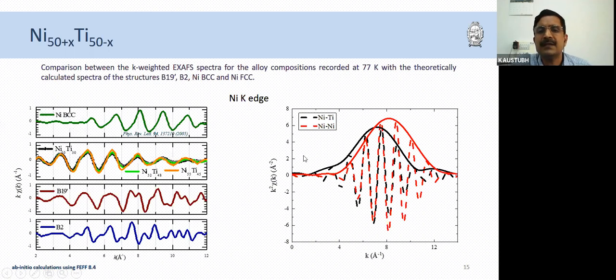And this could be because if I plot the K-space amplitudes of nickel scattering and nickel titanium scattering, then you can see that the maxima of this amplitude is at about 7 angstrom inverse in the case of titanium, whereas when you replace titanium with nickel, the maxima of the amplitude moves higher to about 8 angstrom inverse. And at higher values of K, it is the nickel scattering that dominates. So probably this is the reason for this behavior.